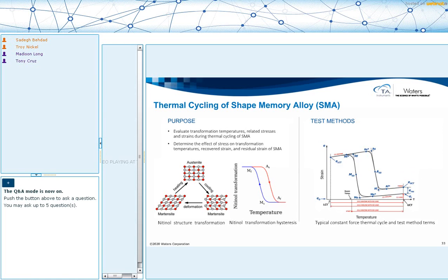bottom at room temperature. You're not applying a load to your sample. You will just increase the temperature to your upper conditioning temperature. These temperatures are usually chosen to be 10 to 30 degrees farther from your transitions for better accuracy. And then you cool it down, and then you heat it up again. So heat, cool, heat. Now you apply a load. That's where you start recording data.